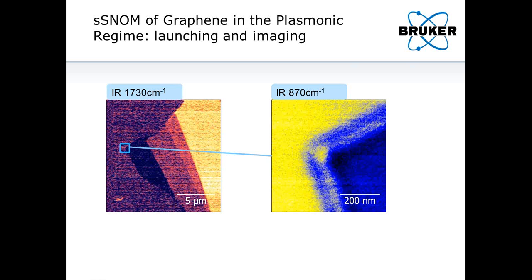In the line profiles, you can see that the spacing between the individual maxima in the graphene plasmon is about 140 nanometers. But also, what's interesting here is that we repeated the same image at much higher scan rates. For instance, the middle image here is at 4 hertz, and then the next image is at 10 hertz. And we saw that we do not lose too much spatial resolution as we increase the scan rate.